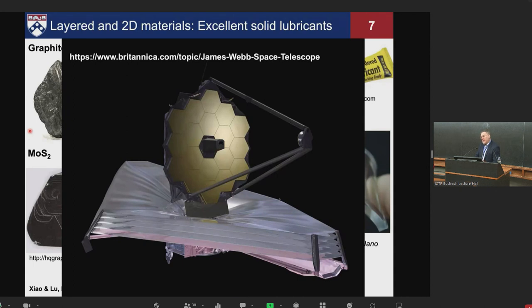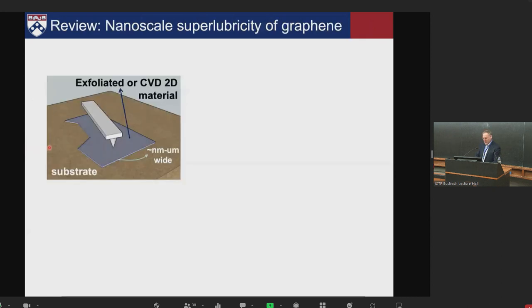And as you may or may not know, moly disulfide in particular is the solid lubricant of choice for space. And we can be thankful to moly disulfide for helping the James Webb Space Telescope succeed. The moving bearings, gears, and other components that are exposed to the space environment have a molybdenum and sulfur containing thin film coating on those parts, and that is the key to ensuring that they don't seize up in the low temperature, high vacuum environment of space. So we depend on these every day, including for some very remarkable applications.